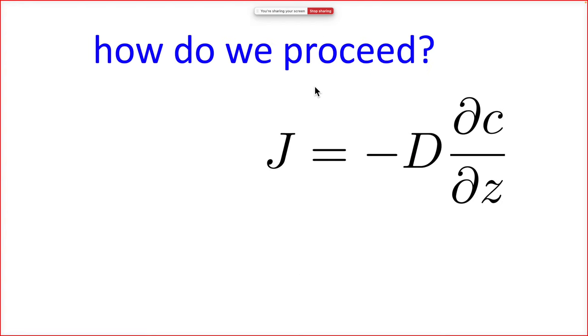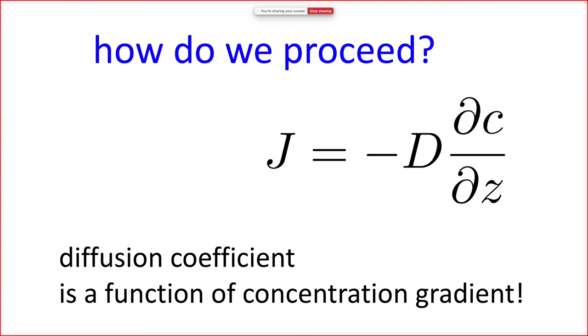How do we proceed? We look at Fick's law again. The diffusion coefficient, if we think about it, is not a constant — it is actually a function of the concentration gradient itself. This is not saying the diffusion coefficient varies with concentration; it is a function of the gradient itself. I will show you some simple analysis first published by Hilliard in the context of spinodal decomposition.